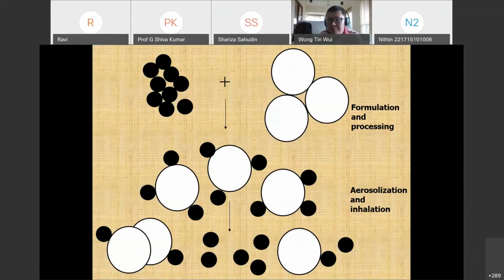So this system appears to be ideal for simple reasons. Upon aerosolization and inhalation, the particles can actually reach the deep and peripheral lung due to the small size. And in the deep and peripheral lung, the nanoparticle can detach from the micro-scale particles and act on the cancer cells, for example. And even if the nanoparticle is not detaching, at least the whole assembly of the particle will reach the deep and peripheral lung, right? So on this note, we deem that micro-scale particles are definitely better than the coarse particles.